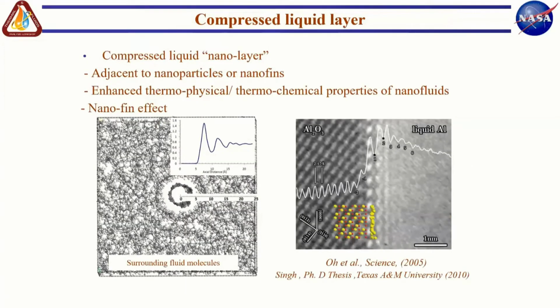And you don't have to take my word for it, because a computational simulation can sometimes give you garbage. So here is a picture on the right that we reproduced from Science, not our work, where they took a picture using a high resolution transmission electron microscope, HRTEM. And sure enough, you can see that on the sapphire crystal, liquid aluminum layers up with a dense layer. And the interesting thing you notice is that liquid aluminum molecules right on the surface of the crystal are mimicking the crystal lattice, actually. So it's spacing up with the same spacing as the top layer of the crystal lattice. So that's experimental evidence of what we show numerically as well.